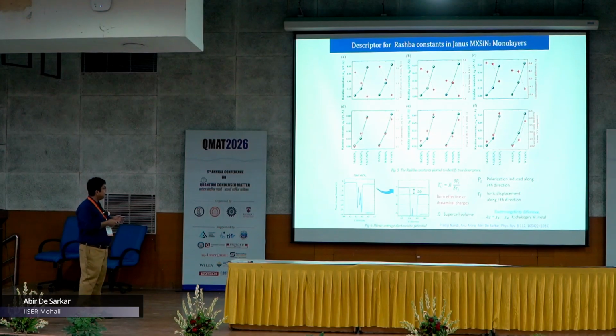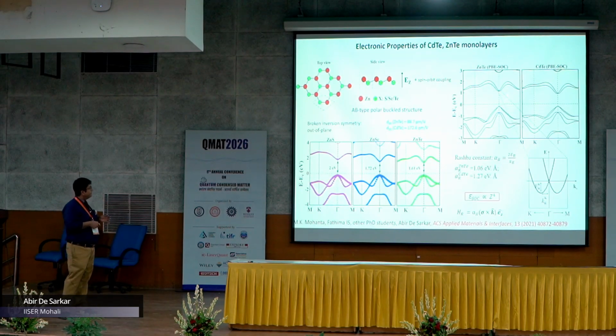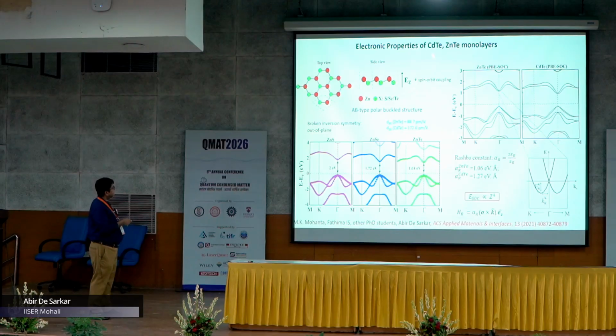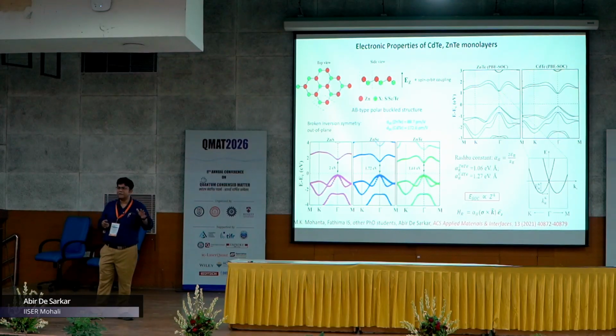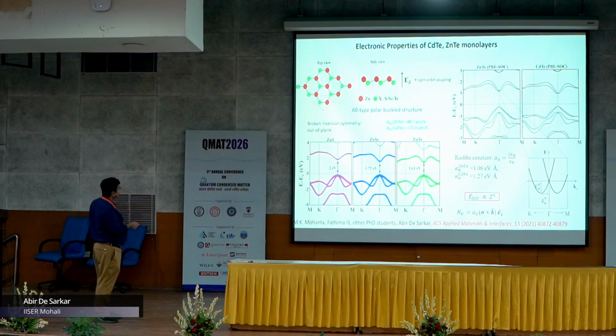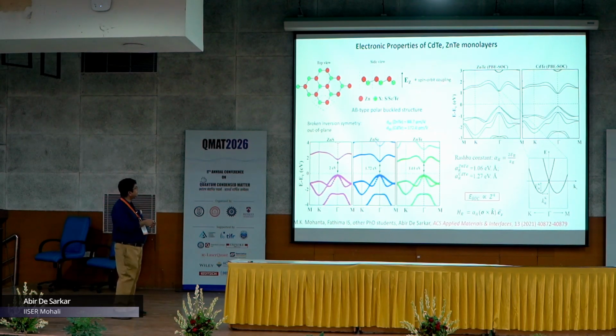And so, if you come across 2D monolayers such as CdTe or ZnTe, these kind of monolayers which have an AB type polar buckled structure, there are several advantages. This obviates the need for the formation of Janus structures. You do not need to design Janus structures, because due to this polar buckled structure, an out of plane electric field intrinsically arises in them, which together with the spin orbit coupling brings about this Rashba type spin splitting in the conduction band. And since cadmium is heavier than zinc, here the Rashba constant is higher.